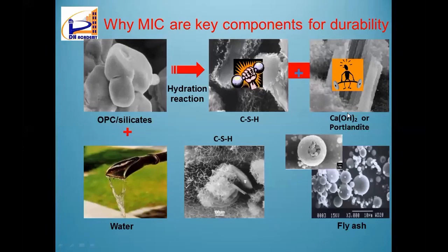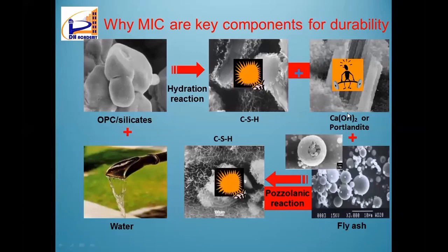So now just imagine, in the same equation, if you have OPC plus water and we are adding mineral admixture like fly ash or slag, what will happen? This mineral admixture, fly ash or slag, will react with the calcium hydroxide. Again, CSH, hydrated calcium silicate product, will come. So this is very, very important, and this reaction is called pozzolanic reaction. So we are eliminating an unwanted material by adding fly ash or slag.